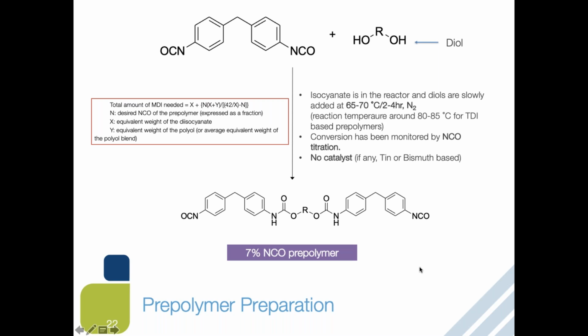This slide goes over the typical way to make a prepolymer. For our study purposes, we prepared various types of prepolymers using different diols. If you're not familiar with prepolymer synthesis, it basically involves a difunctional isocyanate and the diols. As you can see here, this shares the basic equation that you can use to calculate the amount of isocyanate and diol in your system to achieve the specific isocyanate percent of the prepolymers. When you're ready to react, isocyanate will be in the reactor, and then you slowly introduce the diols to prepare the prepolymers.